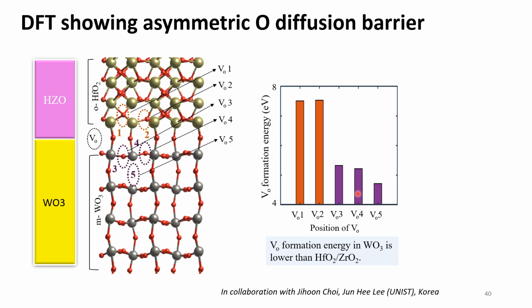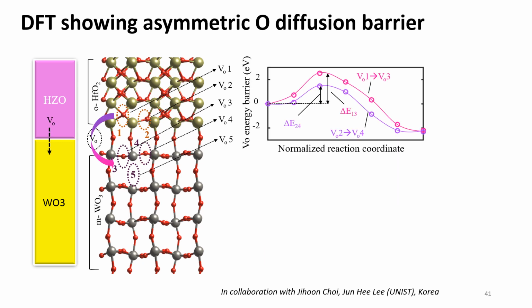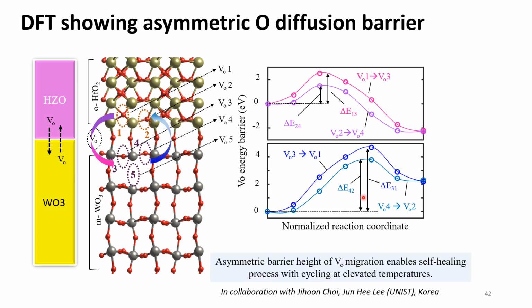Now, why is this important? This is important because it means tungsten oxide can generate more oxygen ions, for which it can act as oxygen reservoir layer. Next, we wanted to see how much energy is needed when these vacancies migrate from one layer to another. So first we have calculated the migration energy of oxygen vacancies when it moves from hafnia to tungsten oxide layer. And for that it needs energy of around 2 electron volt. But when oxygens from tungsten oxide would migrate to hafnia, it would need energy of around 4 electron volts, meaning vacancies will need higher energy for going from tungsten oxide to hafnia layer.